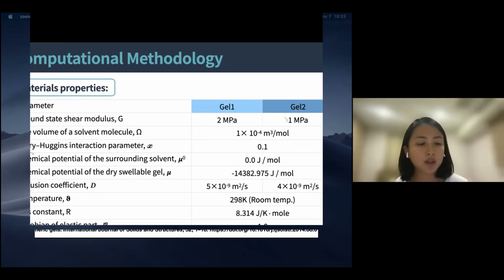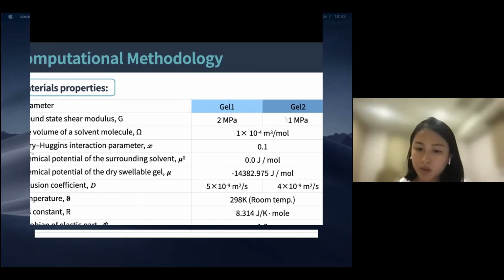So the shear modulus of gel 2 is lower than gel 1. It is because there are more particles in the gel. The particles cause a lower concentration of the polymer, so it will also lead to a lower shear modulus of the material. Then for the diffusion coefficient, since the particles occupy more space in gel 2, the diffusion rate of the liquid and the degree of polymer cross-linking will be lower, so there will be a lower diffusion coefficient in gel 2.